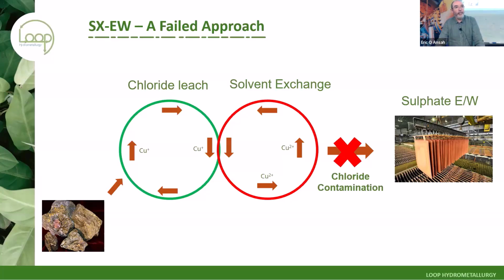Secondly, even if you were successful in performing an SX into a sulfate media, then you immediately lose the major advantage of being in a chloride, and that is we recover our copper directly from the 1+ state. In sulfate, you don't have a 1+ state, so you're back to 2+, and that means you need twice the number of electrons per atom of copper for every atom of copper that you're going to produce. And thirdly, sulfate electrowinning is limited to 375 amps per square meter before you stop getting flat plate cathode. Our new cell that we have developed and I'm going to talk about, we believe it will operate up to 2000 amps per square meter. So we can produce high purity dendrite directly with approximately 20% of the tank house footprint.